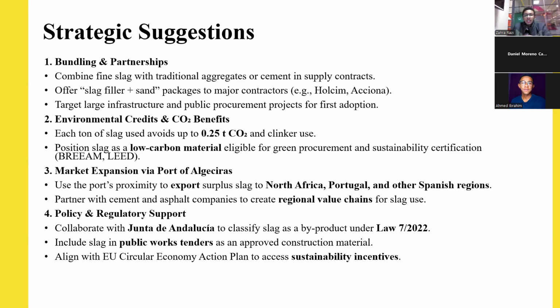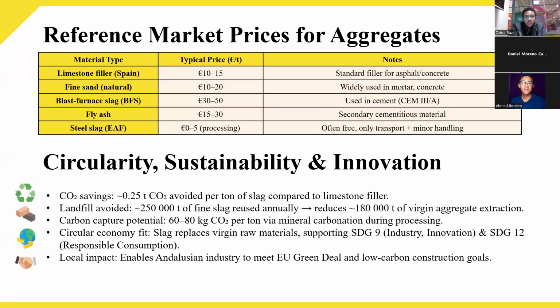Thank you, Daniel. And now, for my part, I will be talking about circularity, sustainability, and innovation. Fine slag perfectly fits the circular economy model. Each ton reused avoids about 0.25 tons of CO2 emissions, prevents 250,000 tons of waste from entering landfills, and saves around 180,000 tons of virgin aggregate extraction every year. Additionally, the material naturally carbonates over time, capturing between 60 to 80 kilograms of CO2 per ton.